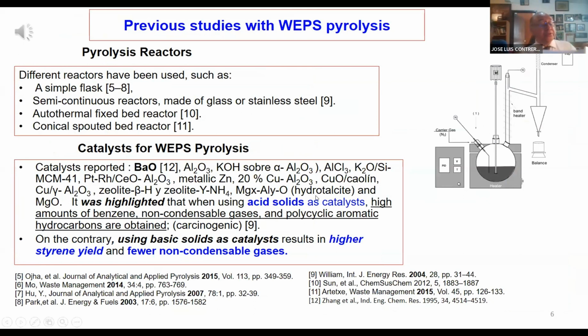Well, the literature review of WEPS pyrolysis can be divided into studies with different types of reactors and catalysts with certain activity and selectivity. A large number of simple flask type reactors made of glass or stainless steel are observed. Then semi-continuous reactors, then autothermal fixed bed reactor, and finally the conical spouted bed reactor. Regarding the catalyst, we have found metal oxide supported metal catalyst, hydrotalcites, and zeolites. It has been found that when using acid solids as catalysts, high amounts of benzene, non-condensable gases, and polycyclic aromatic hydrocarbons are obtained. On the contrary, using basic solid as catalyst results in higher styrene yield and fewer non-condensable gases.